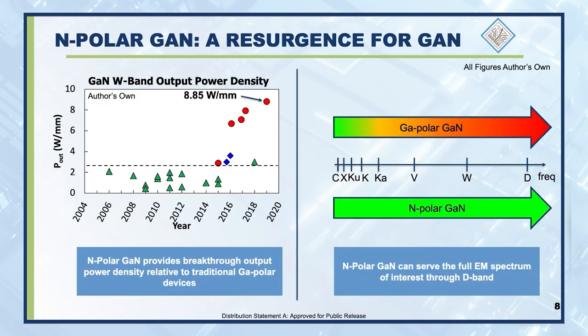To conclude, I'd like to say that nitrogen polar GaN is actually a resurgence for gallium nitride, very apt for this summit. And the reason is that gallium nitride had flattened out in its performance at millimeter waves for many years. Here's the performance of gallium polar GaN as a function of time, and it was all below this 3 watts per millimeter line. Thanks to nitrogen polar GaN, we have broken out of this funk, and we are up at very high frequencies, very high power densities at W band, which is 94 gigahertz.